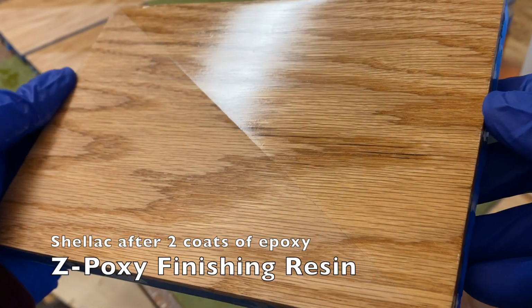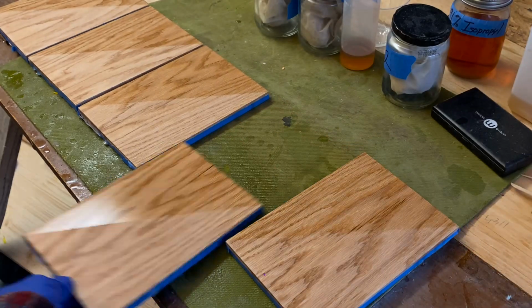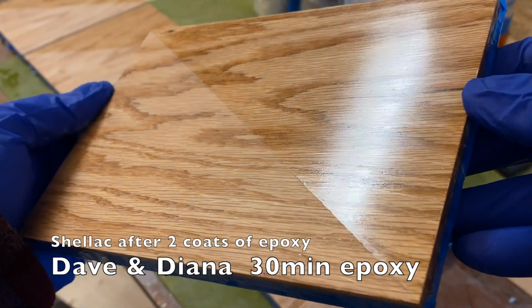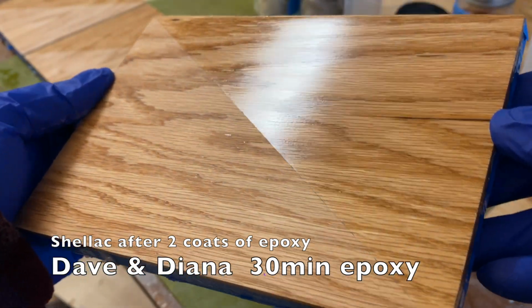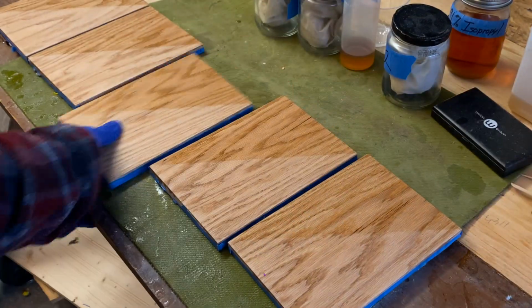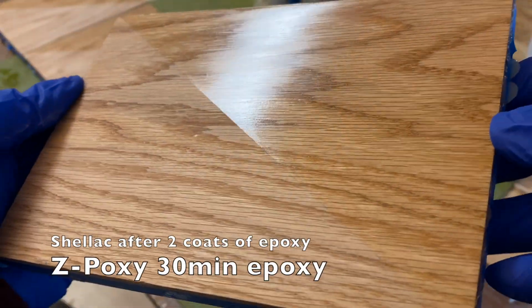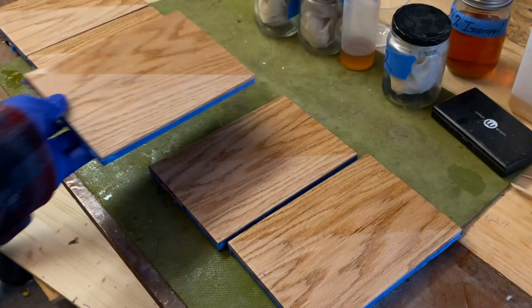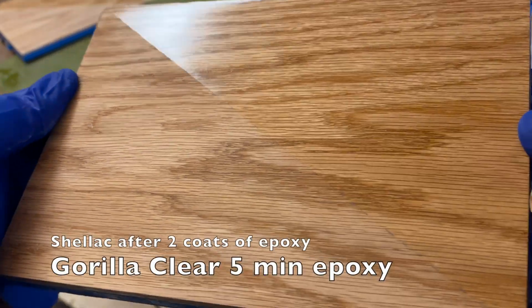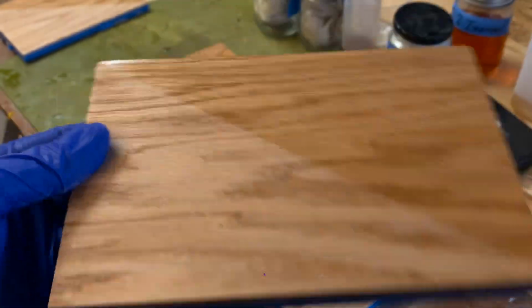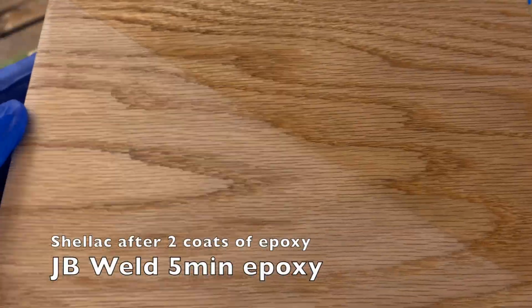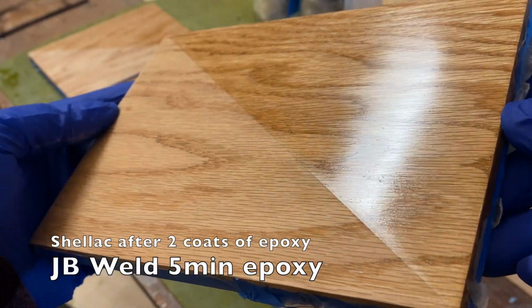And for all intents and purposes, it seems like 2 coats of epoxy was enough to fill the grain with all of these, which surprises me because usually it takes me about 3 coats of epoxy to get to this point. I wonder if mixing these epoxies in cold temperatures resulted in a thicker application, thus allowing for more product to be filling the surface of the boards. Then the mixtures might have expanded even more while drying in a warm environment.